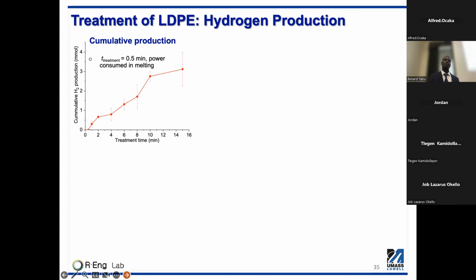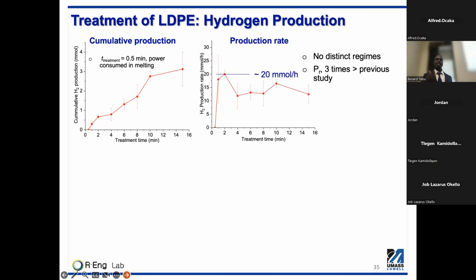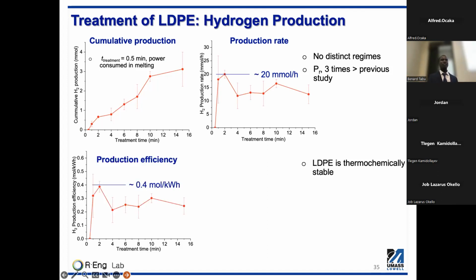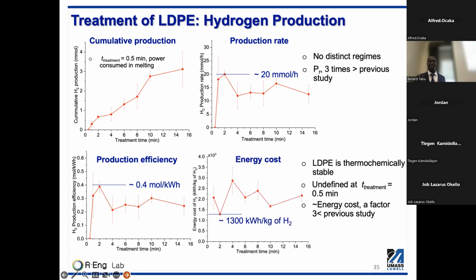We also look at the treatment of low density polyethylene. Here we see that the cumulative hydrogen production increases with time, not as rapidly as in the first phase. The hydrogen production rate increases up to a maximum and then decreases. The overall trend decreases slightly, and it's difficult for us to distinguish between the two regimes. The hydrogen production efficiency follows the same trend as the hydrogen production rate, and the minimum energy cost of production is an inverse function. This is a factor of 3 times less than what we had in the first phase of our study.